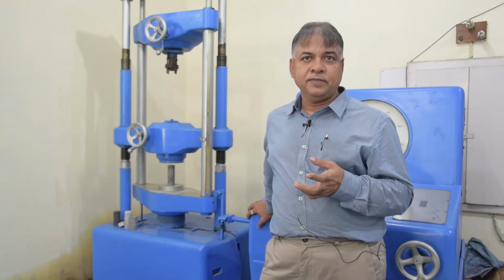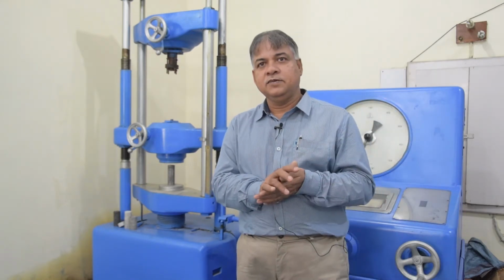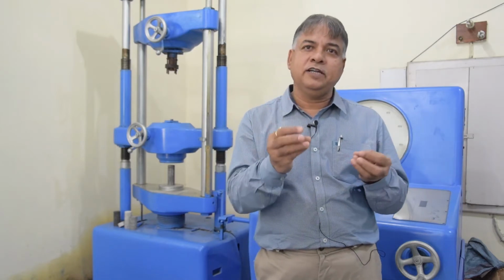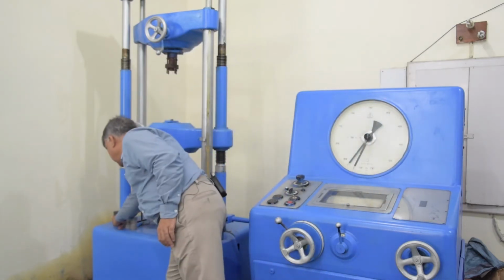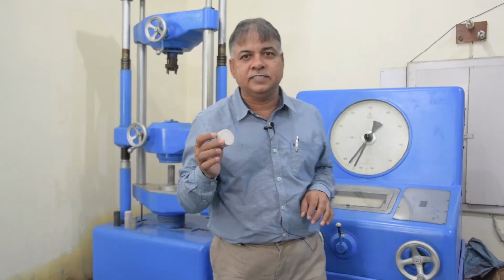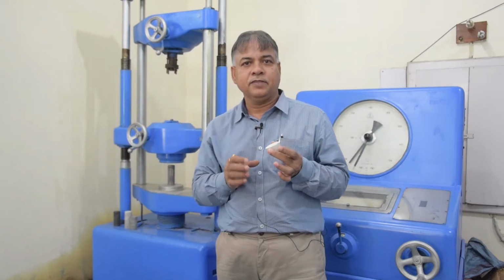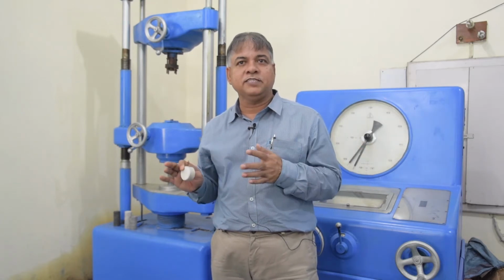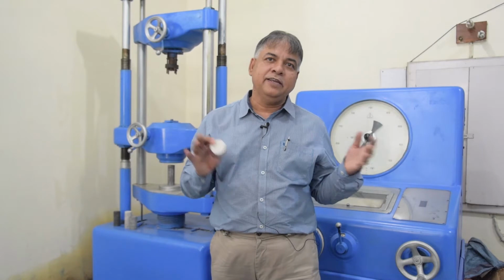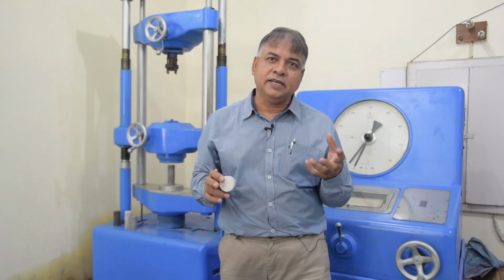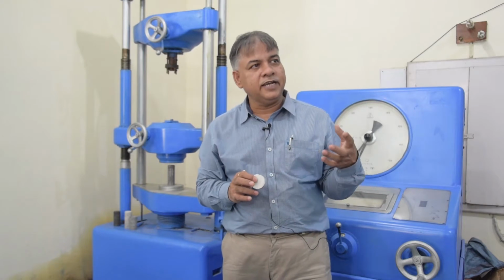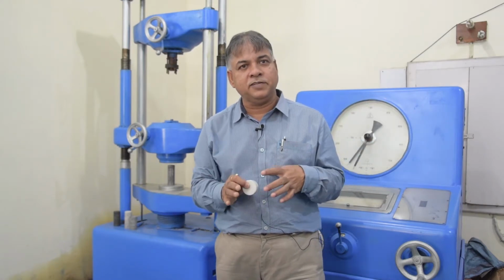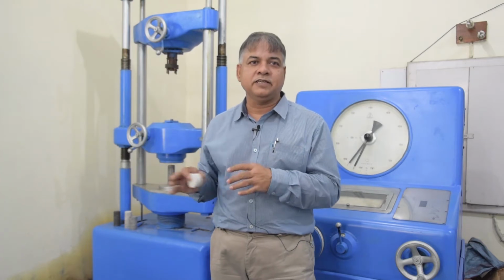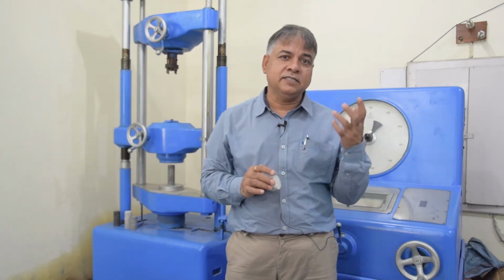That is important. When you compare it with tensile strength, we have a cage in which, if you put a small specimen of this kind in a tensile Brazilian cage, we get the tensile strength. The ratio of compressive strength to tensile strength is of the order of 3 to 121. There are certain kinds of rocks which are only 3 times, meaning their tensile strength is 1/3 of the compressive strength. At the other end of the spectrum, there are rock types in which the tensile strength is 1/121 of the compressive strength of the rock.